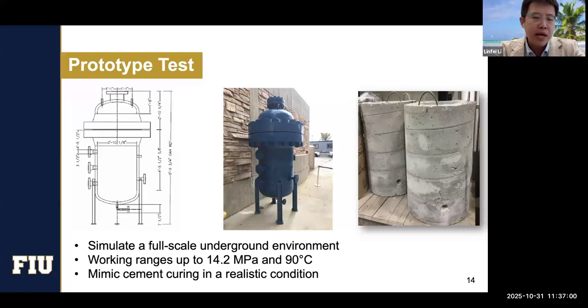Regarding the capacity of this pressure vessel, we'll be able to do a full-scale underground environment simulation. It can pressurize up to 14.2 megapascal. Imagine if this is fully pressured, it's going to be like a small-scale nuclear bomb. And it can also hold temperatures up to 90 degrees C. We use that to mimic the cement curing in a realistic situation.